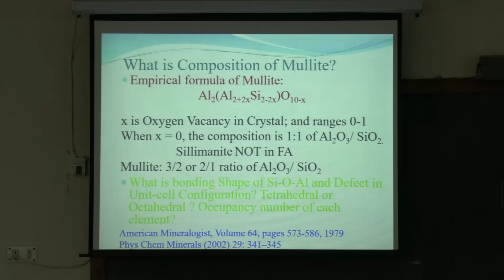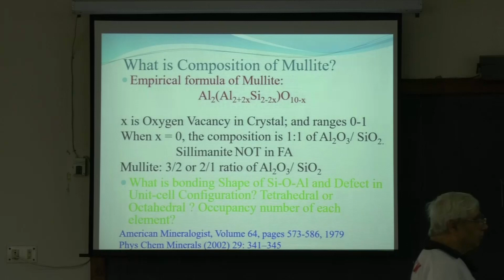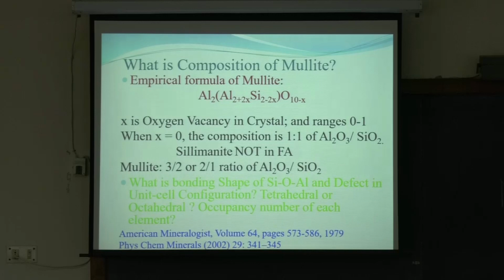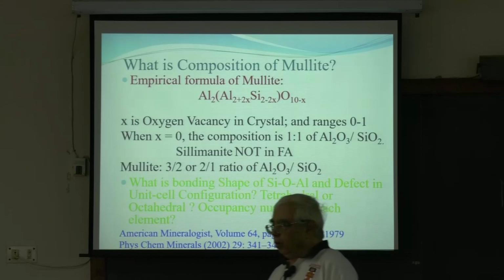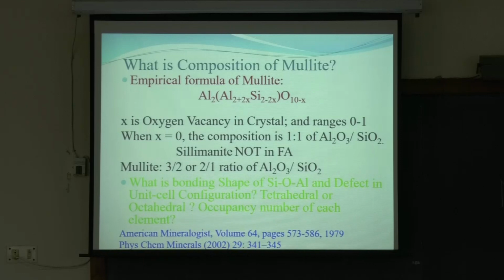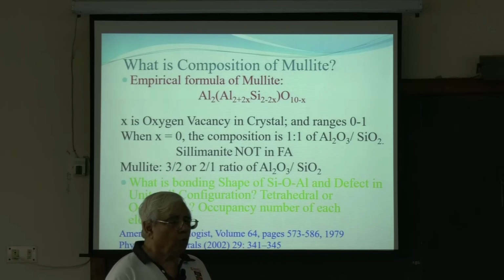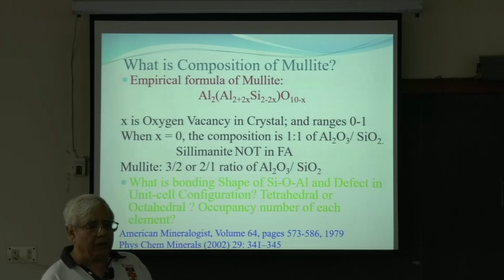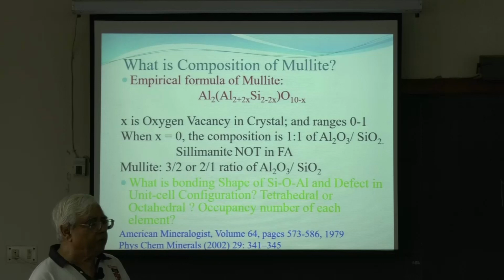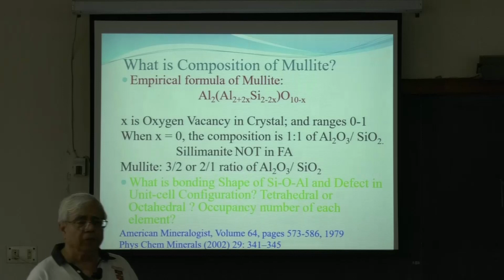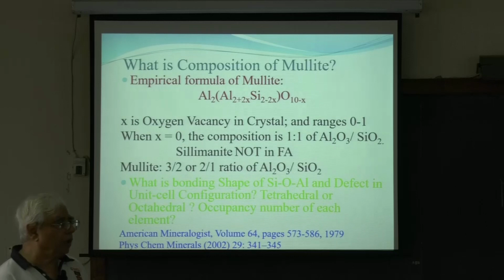Just going back to that semiconducting thing, like my present researcher who has been working on the dielectric properties of fly ash epoxy composites, he found that those two composites which have the highest values of the real and imaginary parts of the dielectric constant both seem to show no presence of mullite. So that was something interesting, and I keep on thinking about it, what to do and all things like that.